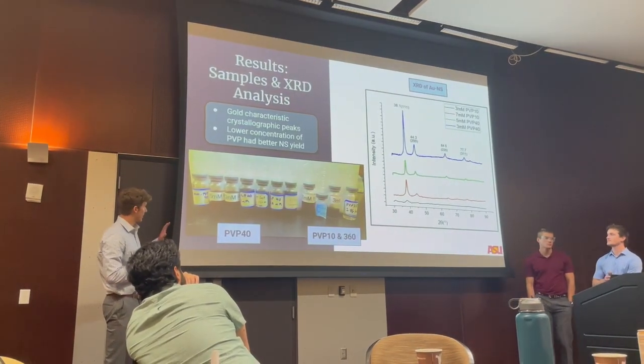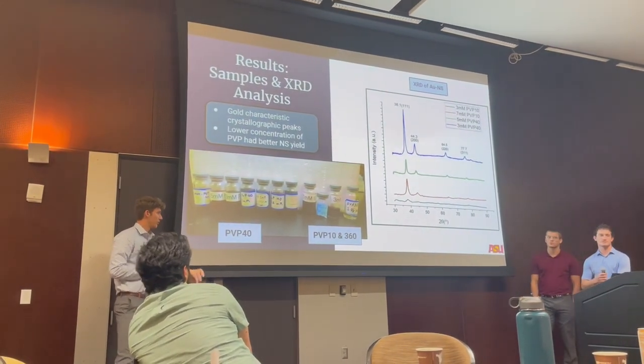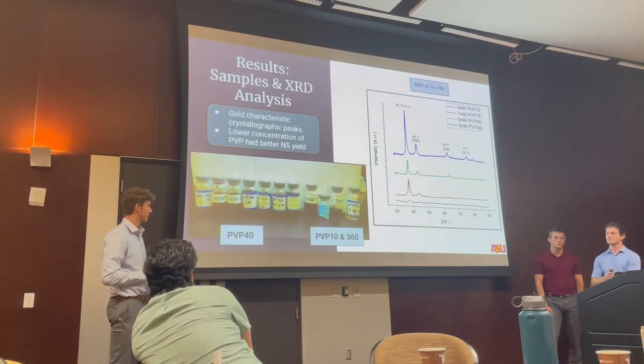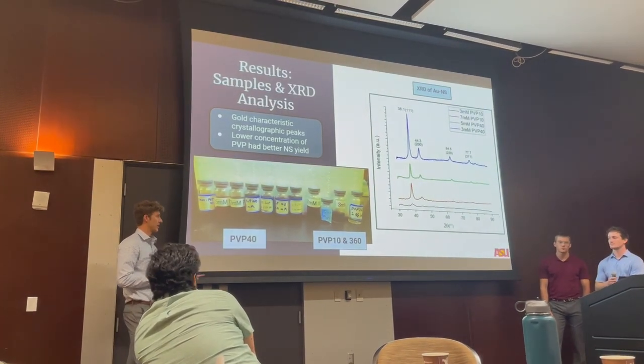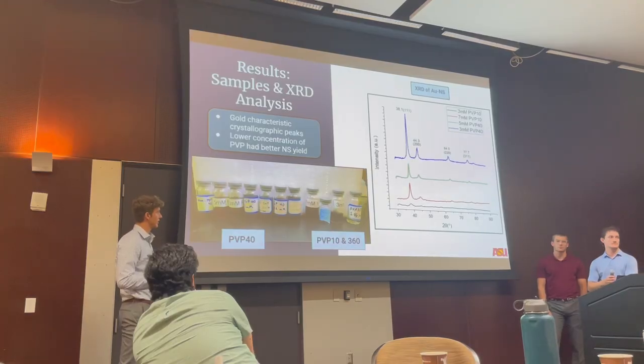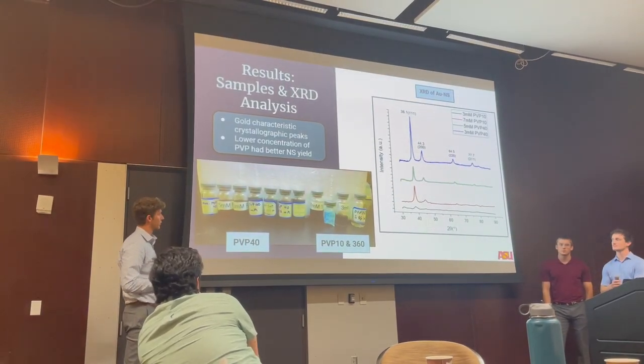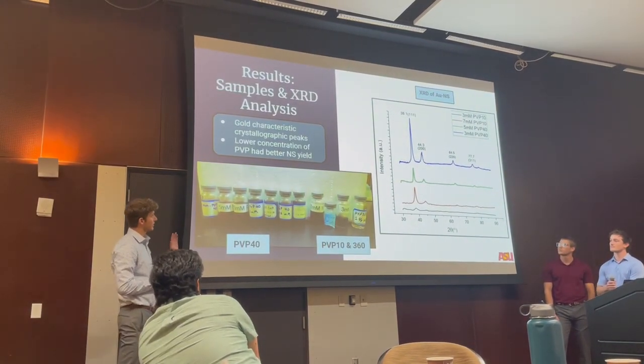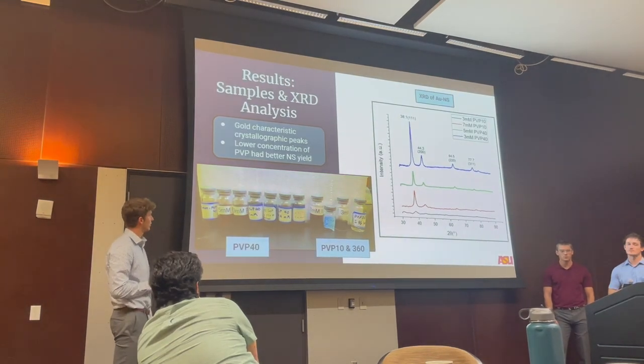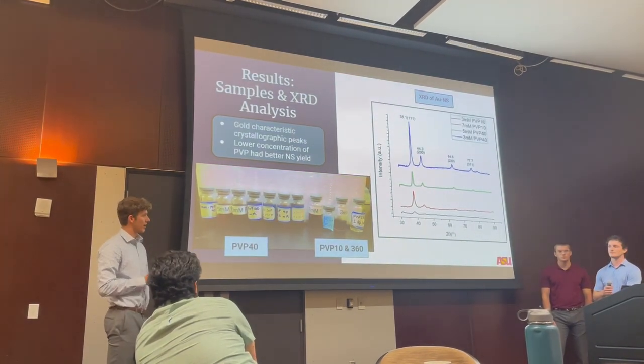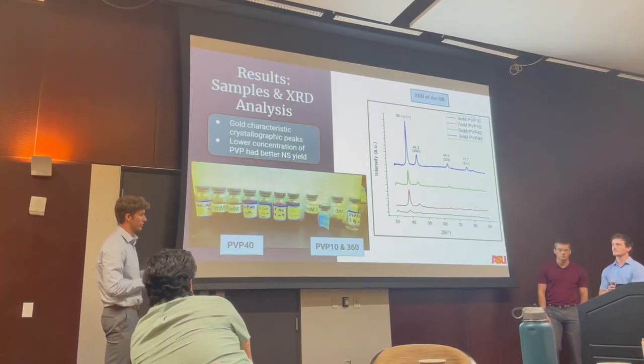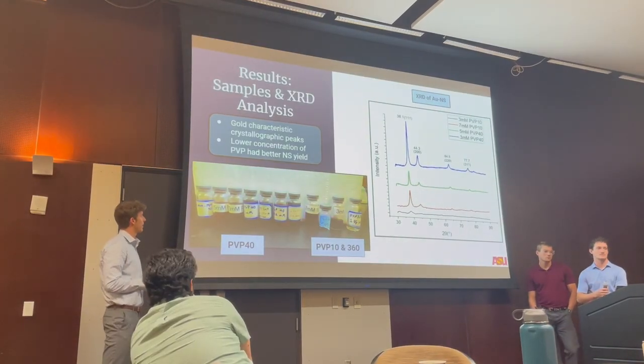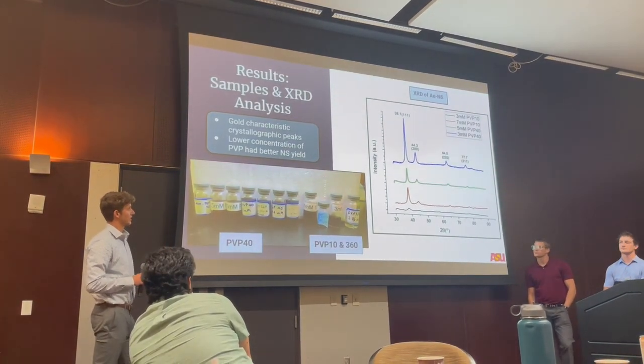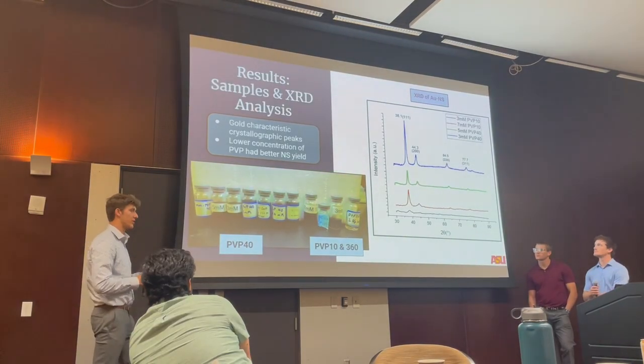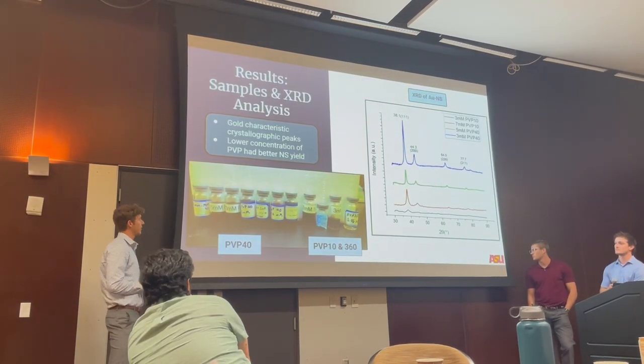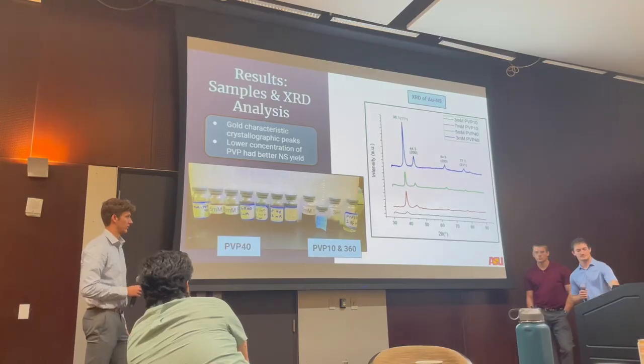So here we have all of our samples that we created. We have 3 different PVP molecular weights. We've got 40,000, 10,000, and 360,000 that we tested. And then we tried them all at different concentrations. On the right, you can see some of the XRD data we got, which shows that we actually created our nanoparticles and they have the right crystallographic planes and growth in them. And then from this XRD data, you can also see that the PVP40 at a lower concentration had the best nanostar yield.